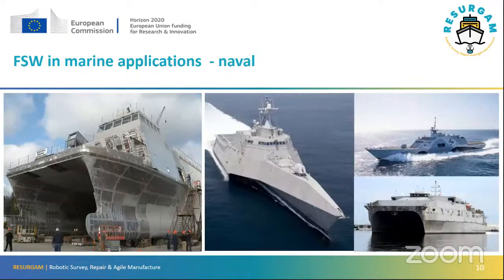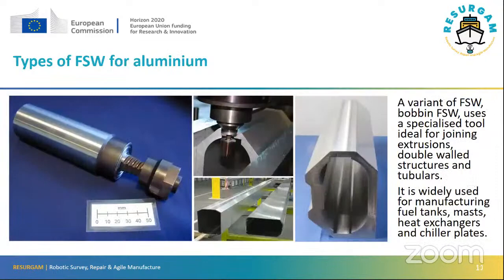It's not just commercial ships, but a lot of military ships use it as well, because it gives incredibly strong, stiff, lightweight joints, which are very resistant to damage. We've got variations upon the technique, which can actually weld through closed sections. For example, it's very simple to use a type of friction stir welding called bobbin welding to join two C-shaped channels to make long tubular structures. So, for example, things like fuel tanks, masts, heat exchangers, or chiller plates can be welded in that manner.